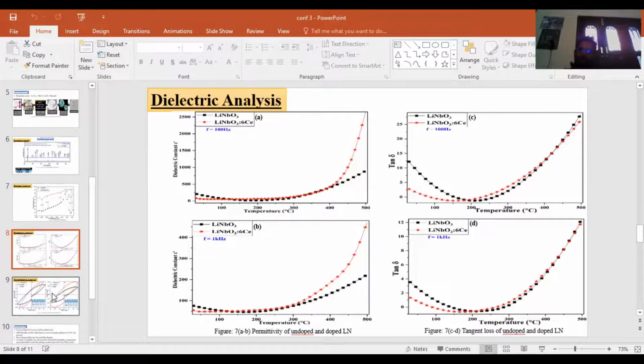For 100 hertz it rapidly increases after 400 degrees Celsius, and for 1 kilohertz it increases after 300 degrees Celsius. And the dielectric constant rapidly increased because of orientation polarization, which I found from the literature and my research work. I also shown here tangent loss, and I can say that there is approximately the same loss for the doped and undoped samples, but the dielectric properties are enhanced.